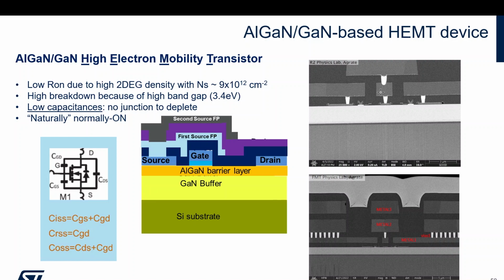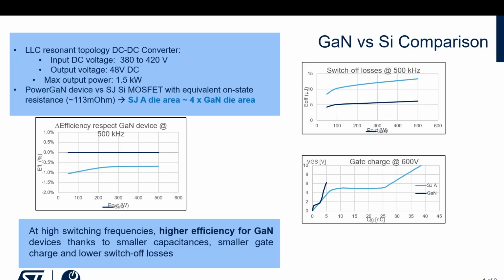But again, also from the reliability point of view, there are a lot of groups that are working on this. But when you look at simple applications, there is no story. If you take this, it's just a non-limiting example, take a DC-DC converter and look at the efficiency between silicon-based and gallium nitride-based, especially if you want to increase the frequency of operation. And increasing the frequency of operation in the final application is beneficial because it reduces all the inductors, all the magnetics and other stuff. Well, it's complex from the material point of view, but in terms of performance, if you go, say, above 500 kilohertz, there is no story.